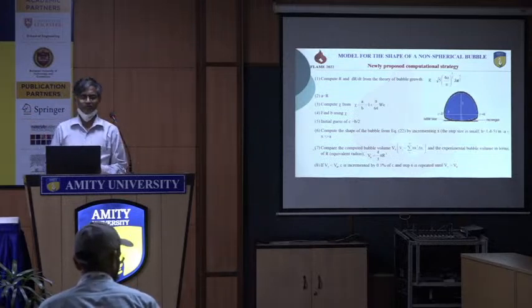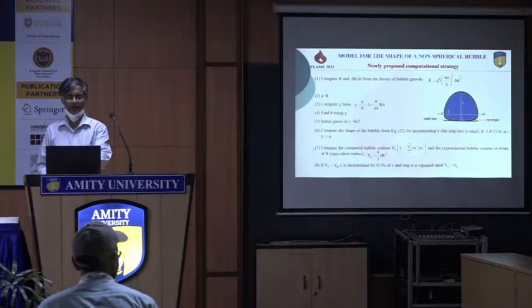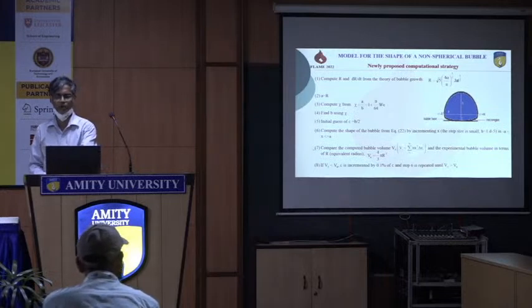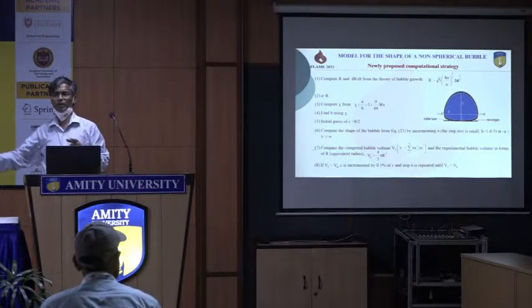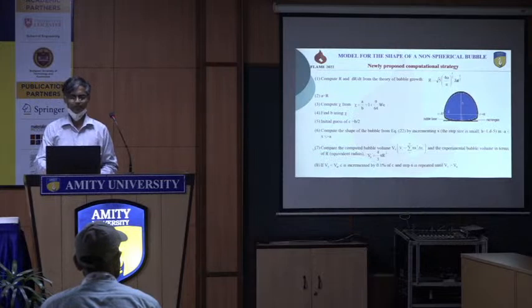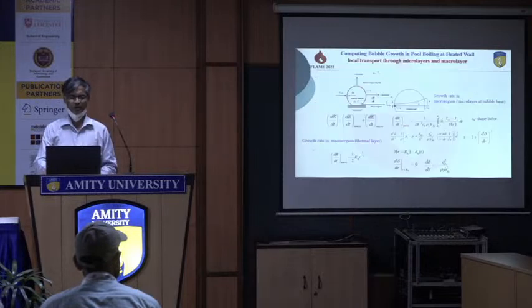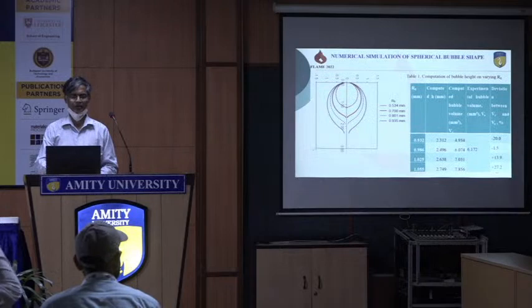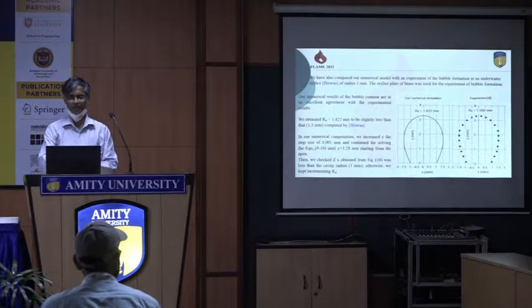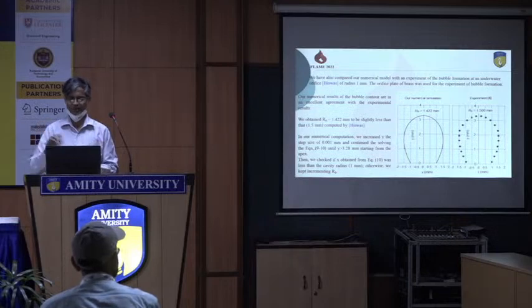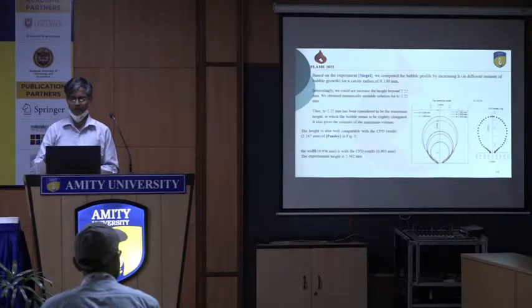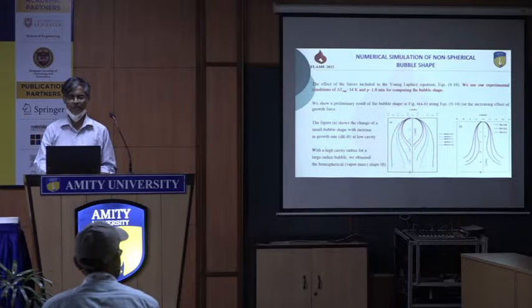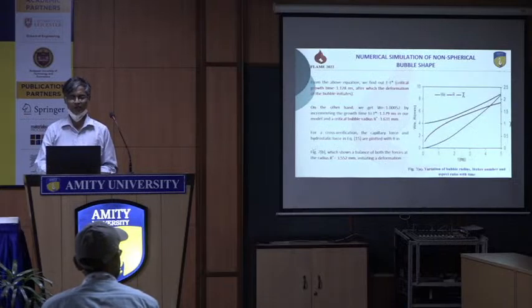In this algorithm, we are calculating from minus R to plus R and generating the profile. A lot of calculation has been done here. I am going quickly to give the result. This is the spherical shape we have got, and it matches the experimental data. The Young-Laplace equation matches the experimental data, but when it is about the non-spherical bubble, it does not match, and that we have addressed here.